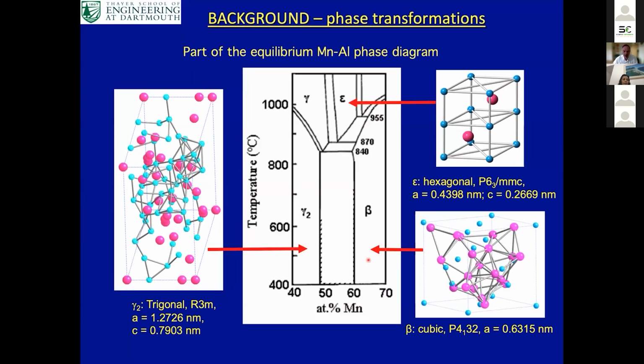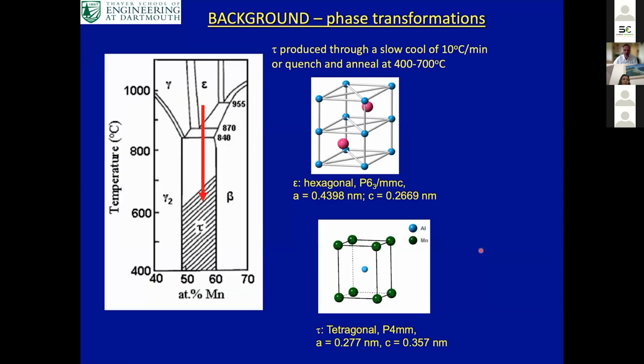So if we look at the phase diagram, this is the manganese aluminum phase diagram, or the central portion of it. At high temperature, we have this phase epsilon, which is hexagonal. And if you very, very slowly cool down to low temperature and hold the material at some intermediate temperature here for a while, you'll get to the equilibrium phases, which are gamma 2, which is this trigonal structure, and beta manganese, which is this complex cubic structure here. However, if you cool not too slowly, or you quench and then re-anneal in the range 400 to 700 degrees C, this phase tau manganese aluminum is produced, the tetragonal phase here. Of course, if you anneal for very long times at intermediate temperatures, you'll get back to the equilibrium phases.